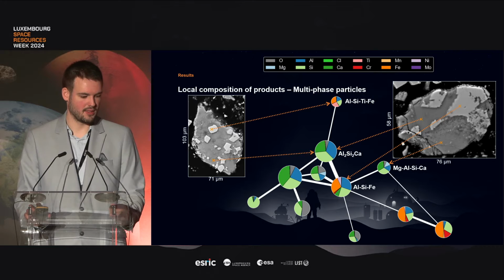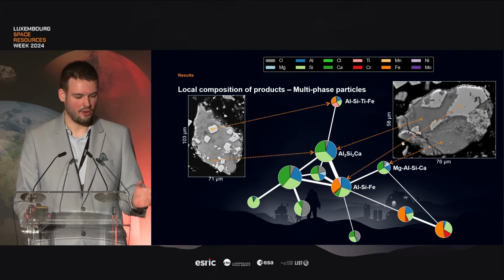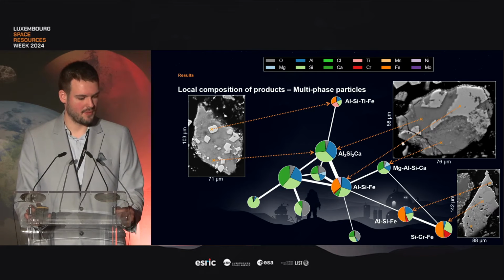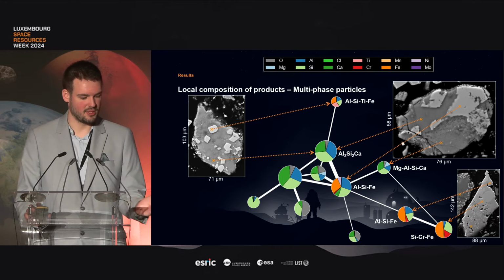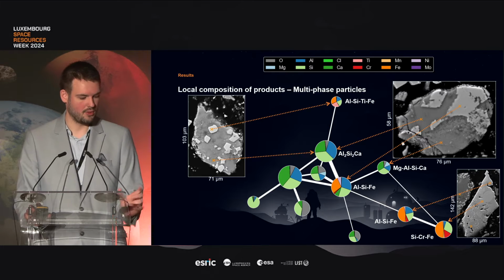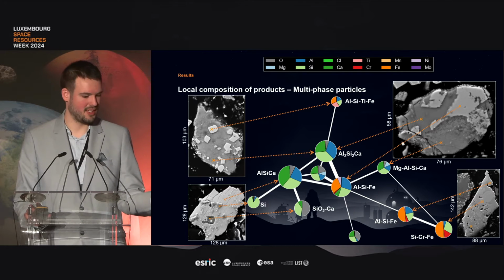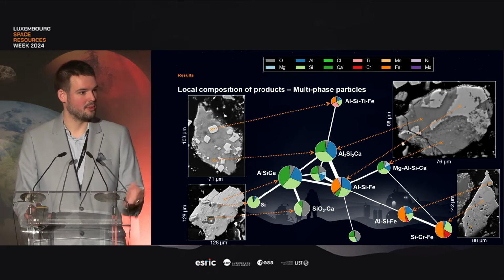And if we do this across all the particles, we can plot this graph of the compositions that are often recurring together in the same particle. And this shows that even though we have some clearly distinct compounds, actually they tend to happen a lot together. For example, the aluminium silicon side and the iron side actually tend to happen together in the same particle. Here, on the iron-rich side, we can also see some different phases: aluminium silicon plus iron, or silicon chromium plus iron, which happen quite often together. And then a last one on the aluminium silicon calcium side. This is also something that happens quite a lot. We can see that we have some reduced silicon, so some quite pure silicon, and at the same time we also have some silicon dioxide. So it is a good example of how complex this material still is.